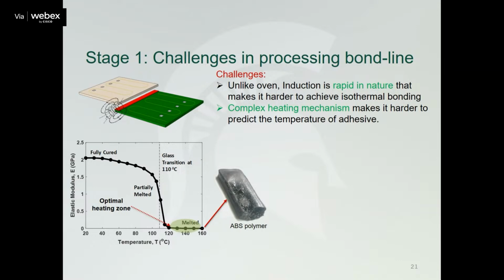for the ABS polymer here, when we try to increase the temperature and at the same time measure the elastic modulus, we heat it from 20 degrees room temperature up to 160 degrees. And you have this transition region where the elastic modulus significantly drops when it's over 100 degrees C, and it's melted and the elastic modulus drops to 0, where you have this glass transition region at around 110 degrees C. And after 160, you have permanent damage to this ABS polymer.